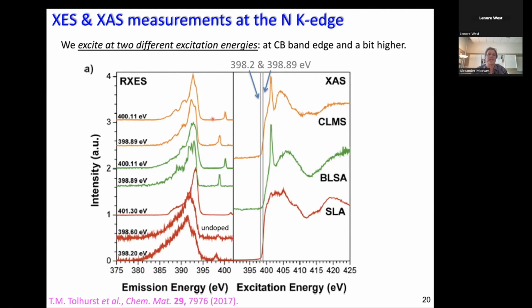Now the new thing is, you need to always distinguish the incoming energy that we use for absorption on the right side, and the emitted energy, which is on the left side. The axis here is the emitted photon energy. So this would be the emission spectra, in other words, as I just pointed out, the valence band. And now these 2 gray lines show you the excitation energies in the absorption. Where do we tune our excitation energies for the 2 different excitation energies, and where do we measure our emission spectra?